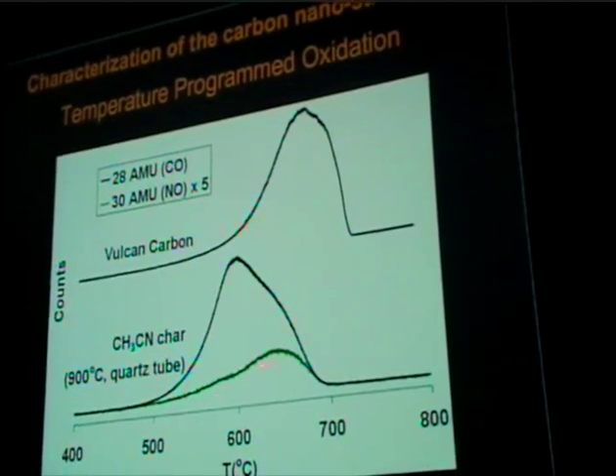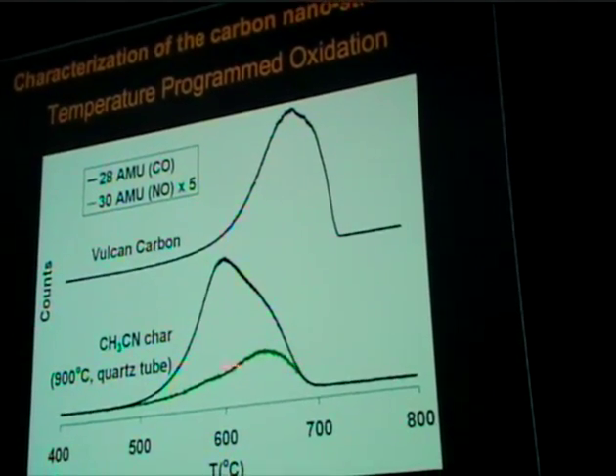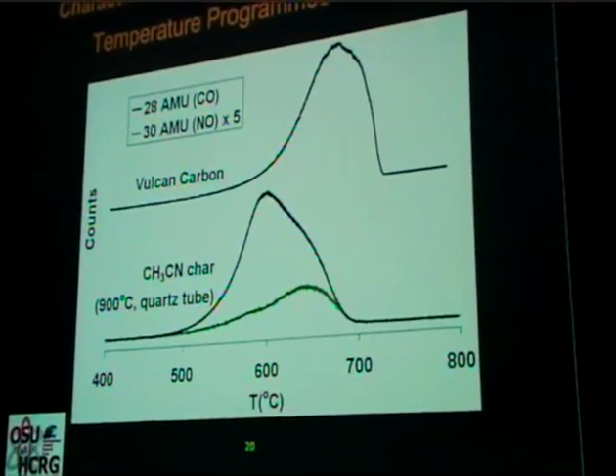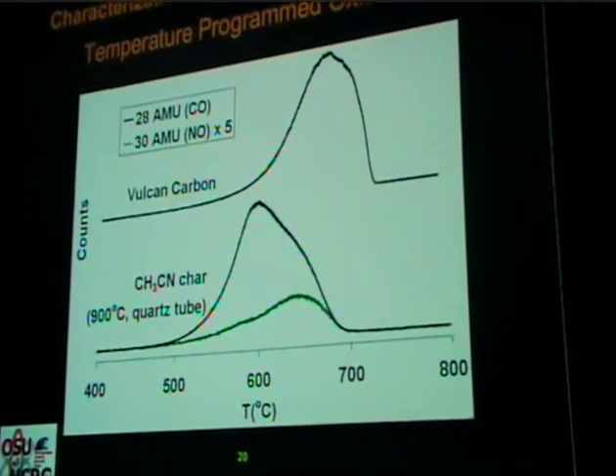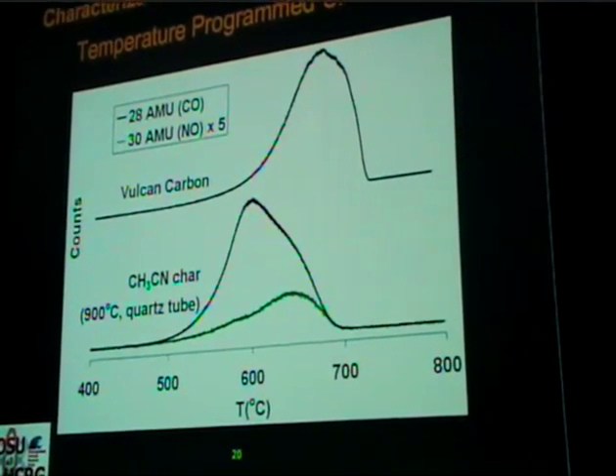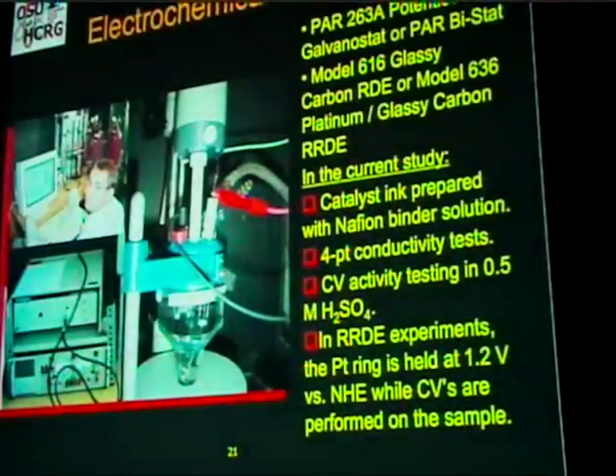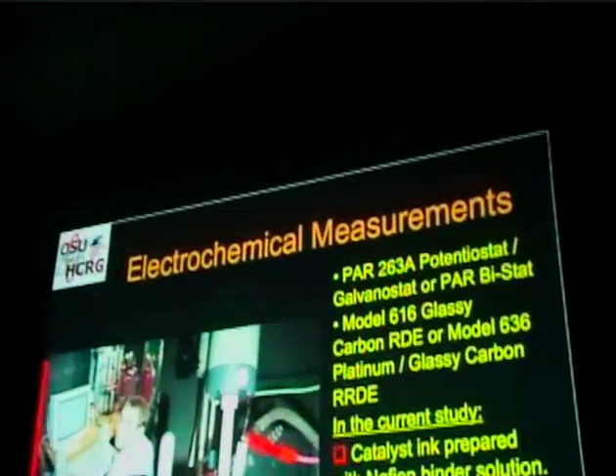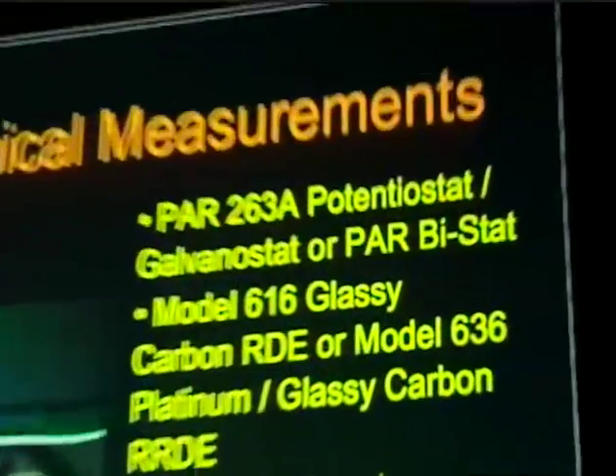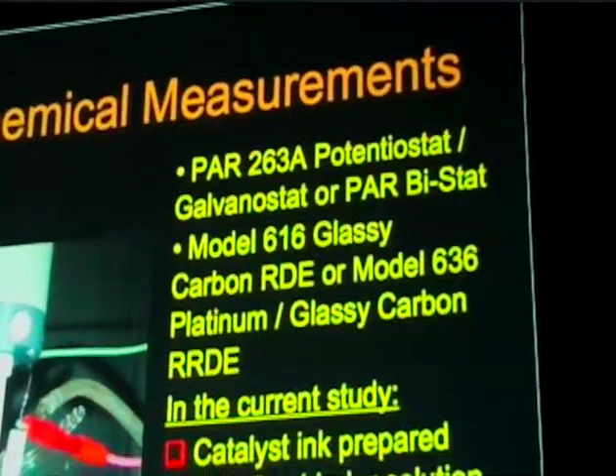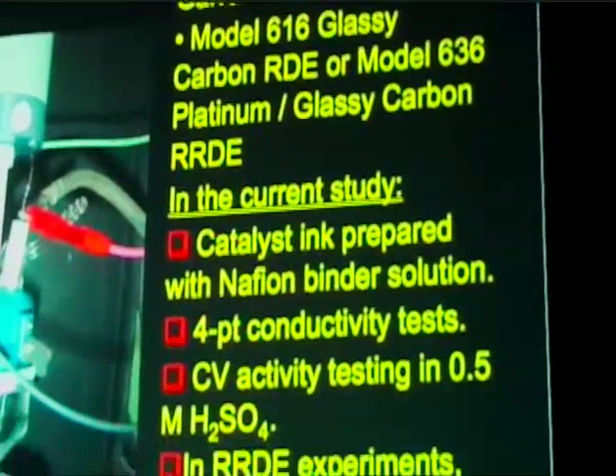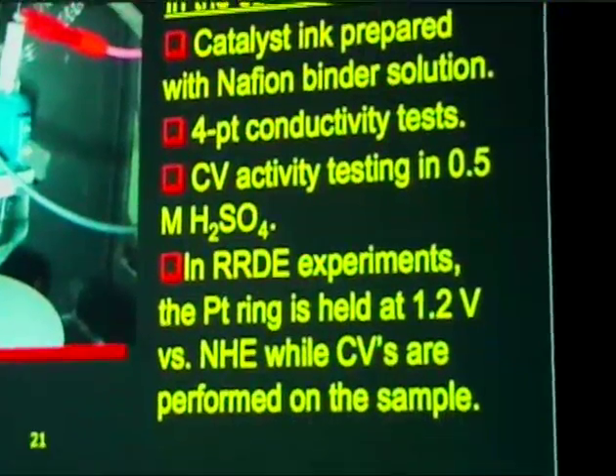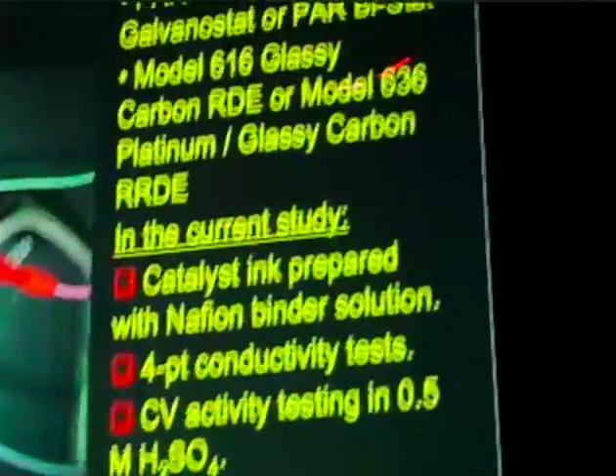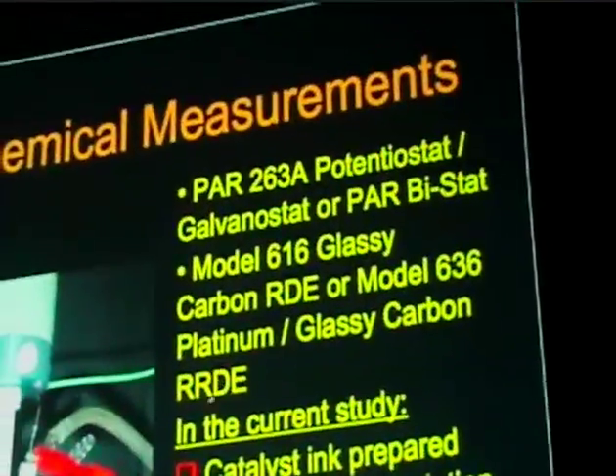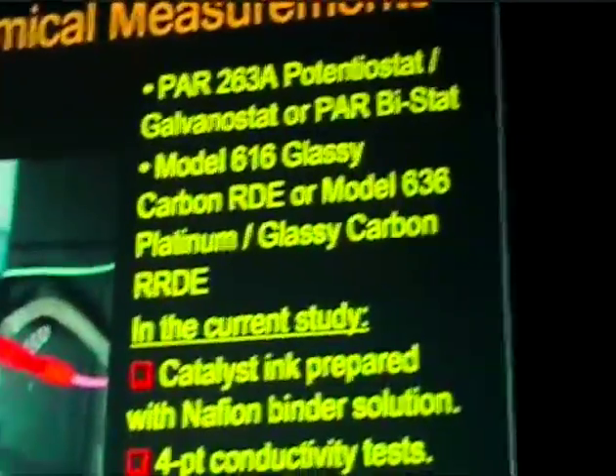But we also see very clearly nitrogen oxide coming from these materials, showing that we have significant levels of nitrogen in these carbon nanostructures. Now, we have looked at the activity of these materials using electrochemical measurements. We are using a half-cell method. We are using either a rotating disc electrode or more recently a rotating ring disc electrode.